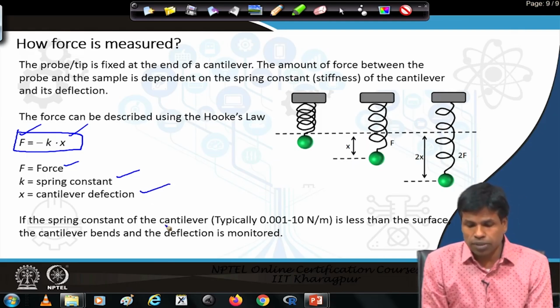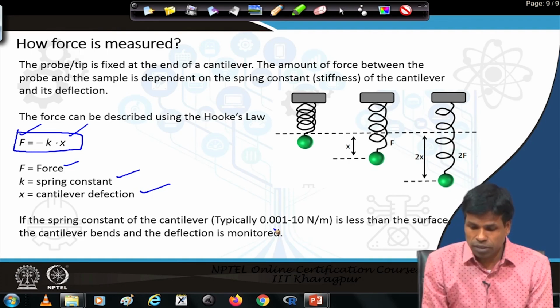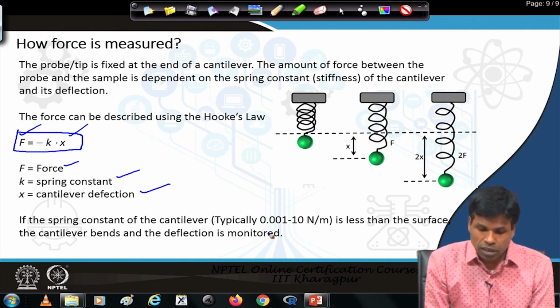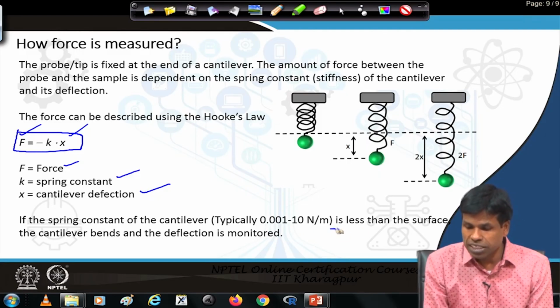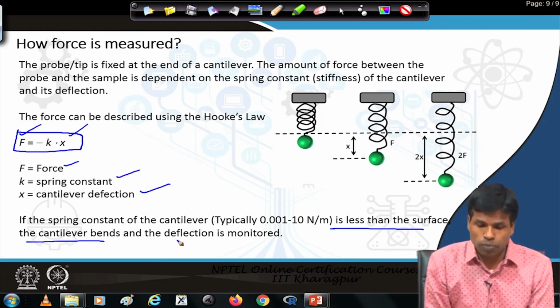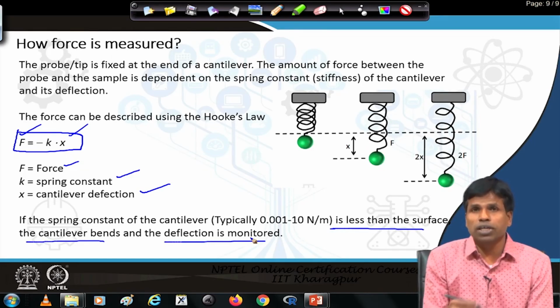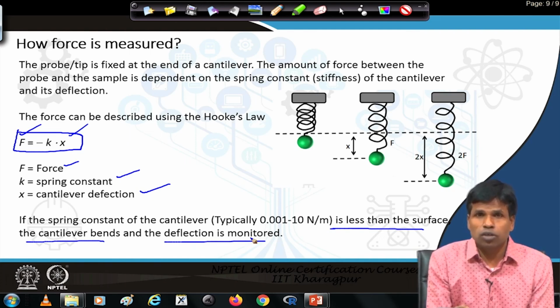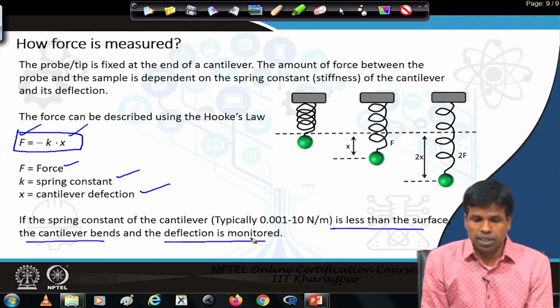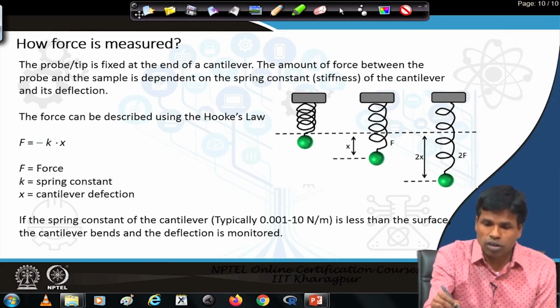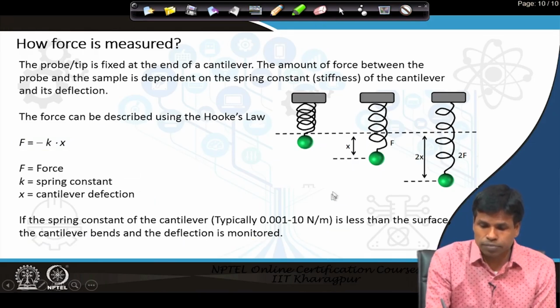The spring constant of the cantilever is normally in the range of 0.001 to 10 Newton per meter. If the spring constant of the cantilever is less than the surface, the cantilever will bend. And deflection will occur, and we can measure that deflection to know how much the cantilever is bending, and then accordingly we can create a 3D image, as you will see later in a more detailed manner.